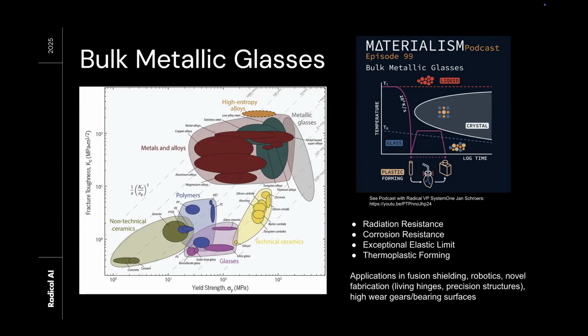Corrosion resistance is an interesting one because in lots of alloys, principally your corrosion will start at grain boundaries. If you have a system with no grain boundaries, then you have no place for corrosive species to attack. This exceptional elastic limit is because you don't have dislocations; dislocations are what allow the deformation of metals to occur easily. You can deform these materials to a large extent, and they'll spring back exactly to their initial shape. This is very interesting for various applications in robotics, like living hinges, like on your water bottle now, where you have a hinge that flips up. It's a continuous piece of material that operates as a hinge.